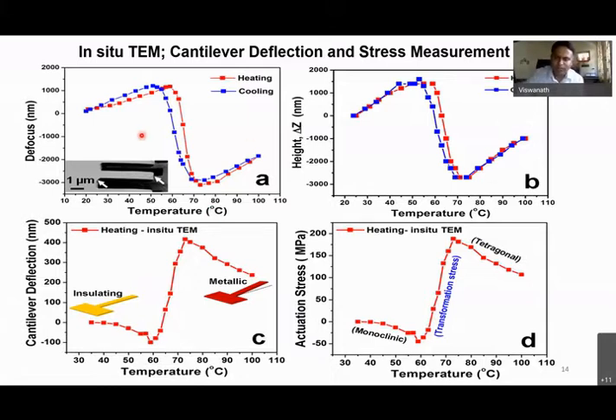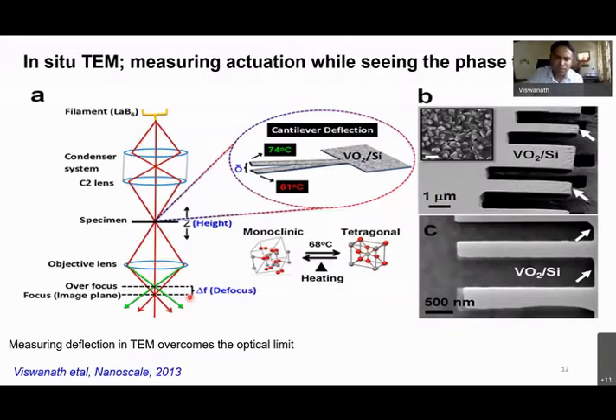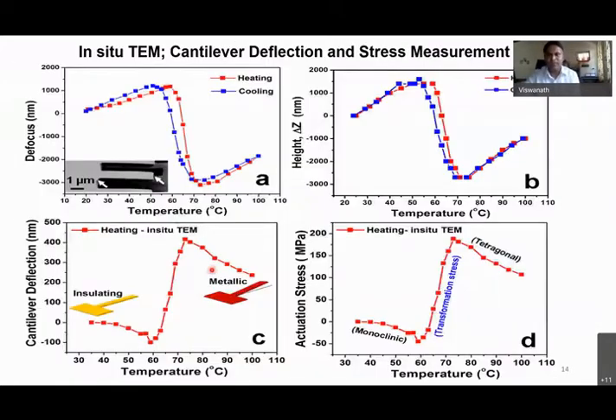We also did the other one. Instead of changing the defocus value, we also have a Z control, so the height can be changed without touching the defocus value. If the cantilever is going up, then I can correspondingly bring my sample down. So that way we can also have the change in height as a function of temperature. Both of them clearly tell me there is an abrupt change in the cantilever tip. As I said earlier, we can do the same exercise for tip and base. The difference will give me the cantilever deflection as a function of temperature.